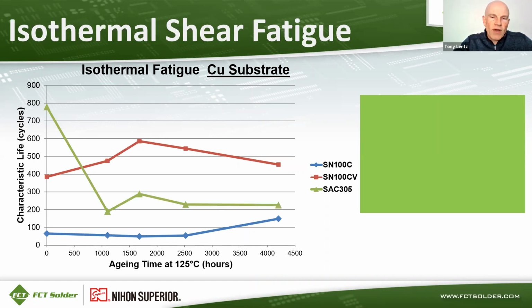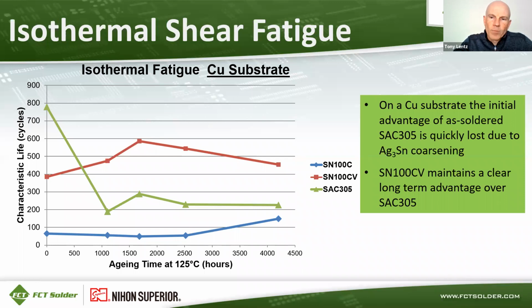And there's the Sac-305 curve in green. So Sac-305 initially has a much higher characteristic life, but then it drops off dramatically by 1000 hours of aging time. And then it holds at that level, which is much lower than the SN100CV life. So the initial advantage of as-soldered Sac-305 is quickly lost due to that coarsening of the Ag3Sn particles, whereas SN100CV maintains a clear long-term advantage over Sac-305.